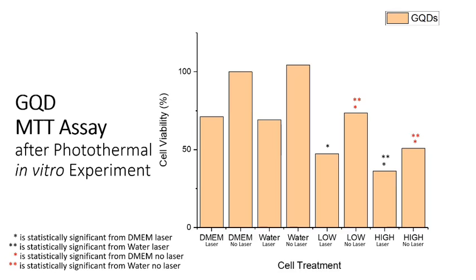But just, again, this is much more toxic than this one, or we know it's much more toxic, but probably what's going on here, the reason why this is still significant from the water and from the DMEM is the toxicity of it. And this one here, we see that it's significant from the water and the DMEM when it's not treated with a laser, so we know they're dying from toxicity. But then we see with the laser, it's only significant from the DMEM. So if there are photothermal properties that are causing any of the cell death here in the low, part of it is due to the water.